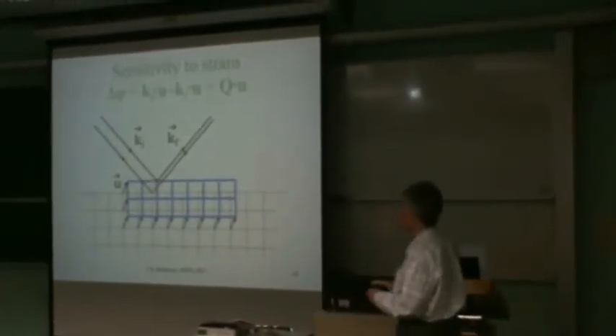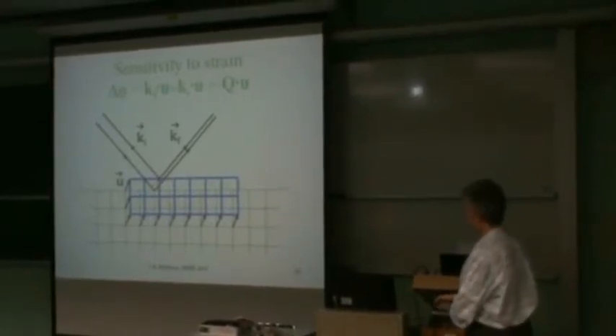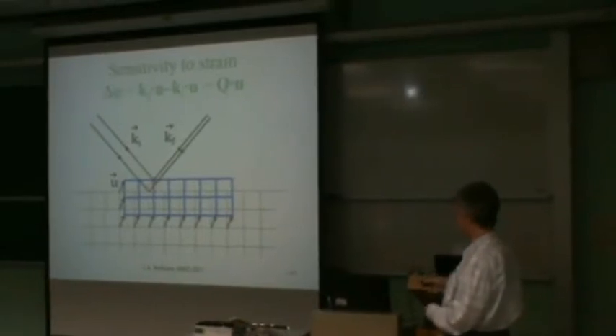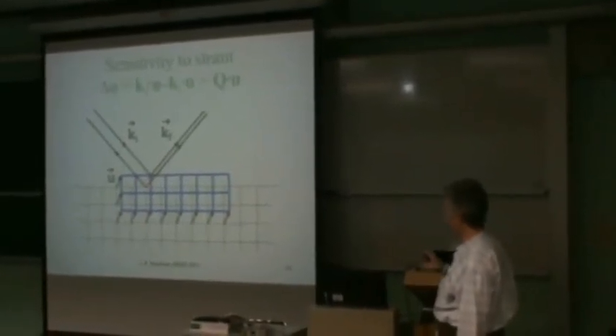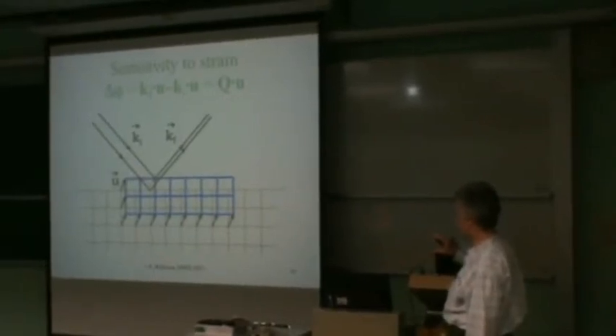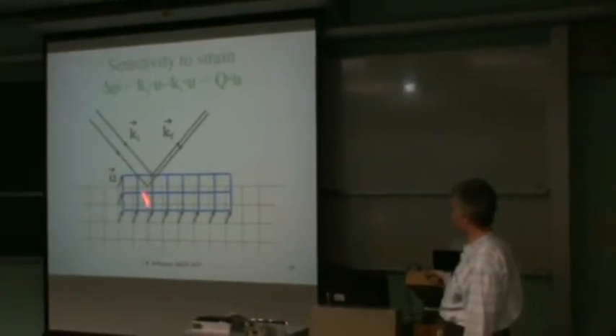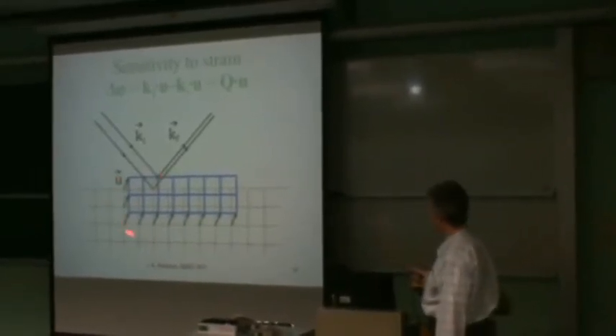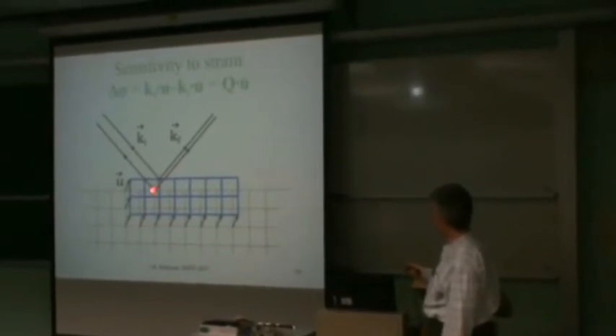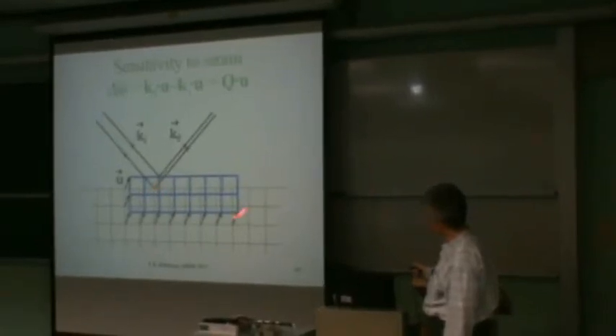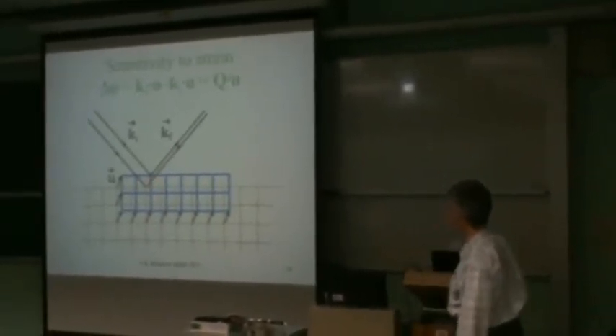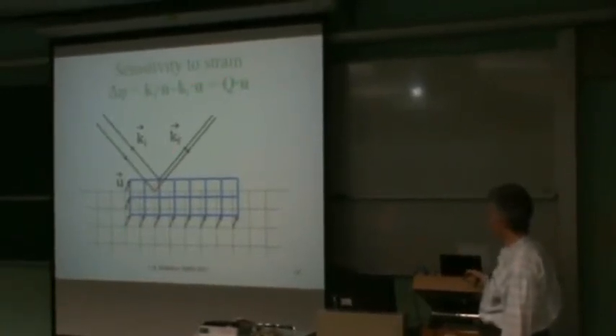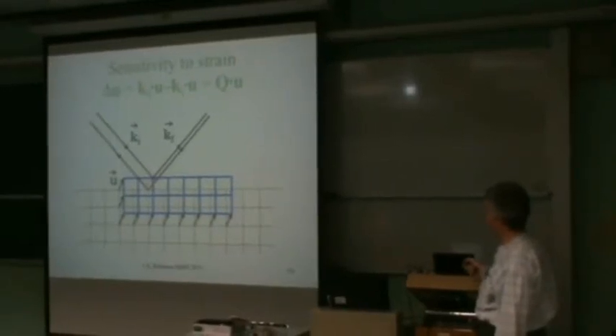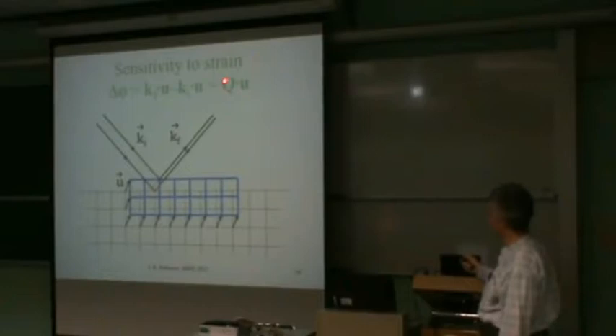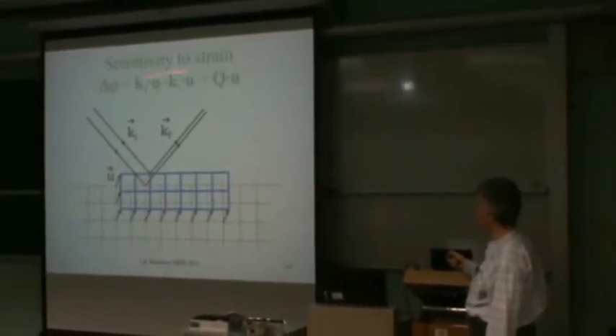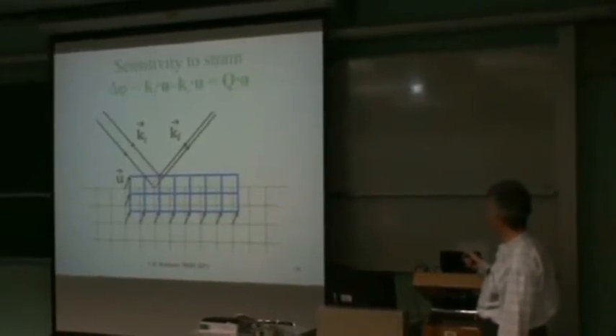And this is the connection between the strain and the phase. The strain corresponds to a distortion of the crystal. So we can think of the crystal as having regions of the material distorted in some way by some displacement field, U here, and the X-rays diffracting from that distorted region are shifted in phase relative to the rest of the crystal by the two red pieces in this construction here. If you add them together, it's just a vector sum of the incident and exit k vectors, and that vector difference is the q vector of the measurement, and you get the phase quantitatively equal to the q vector projected onto the displacement field.